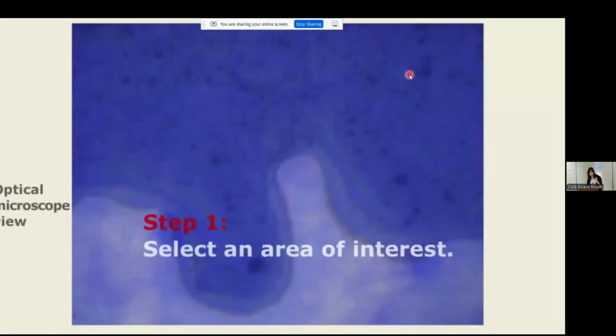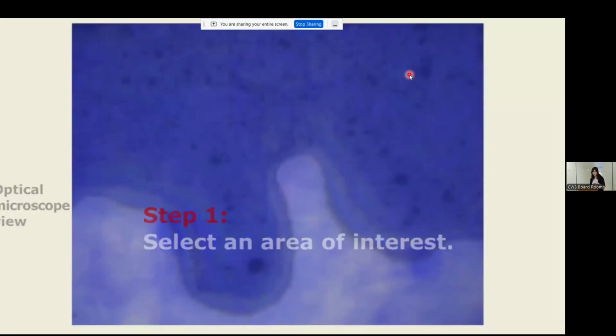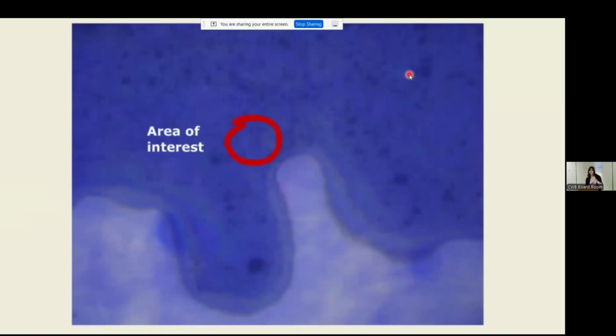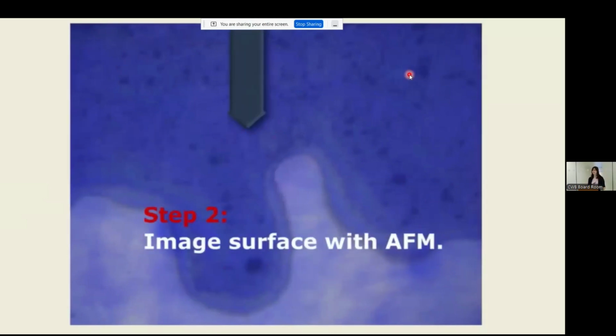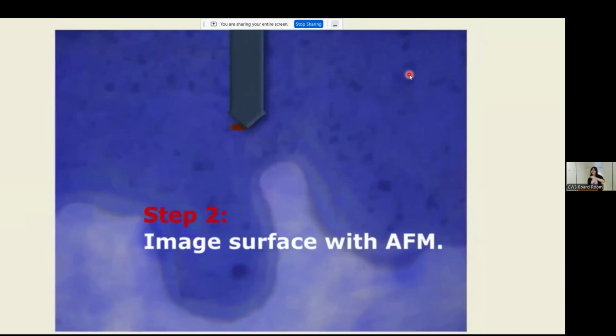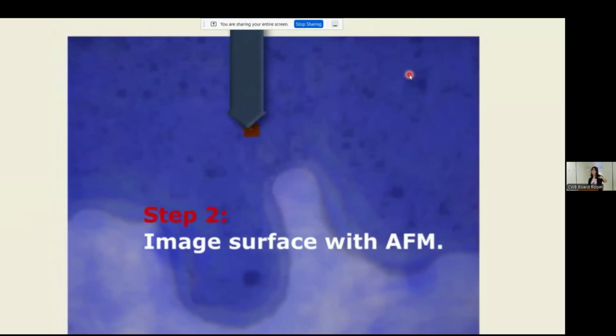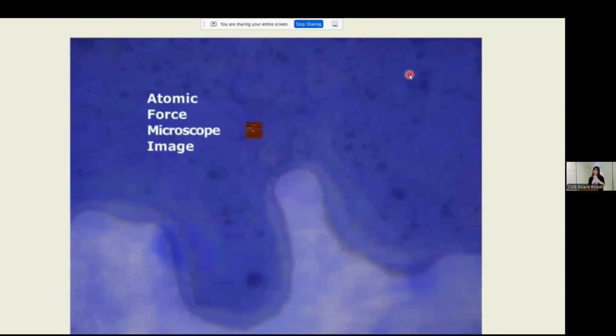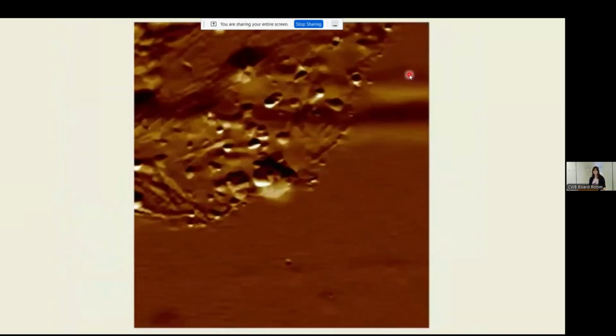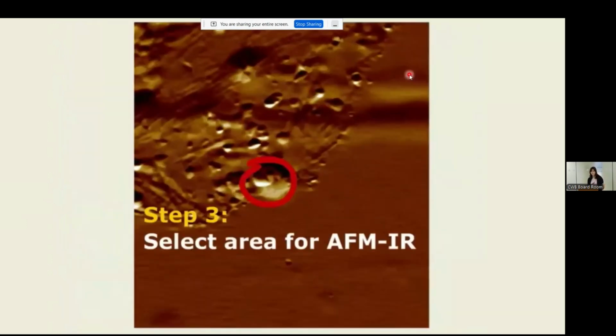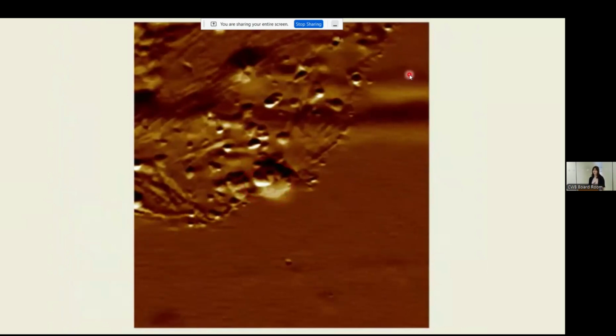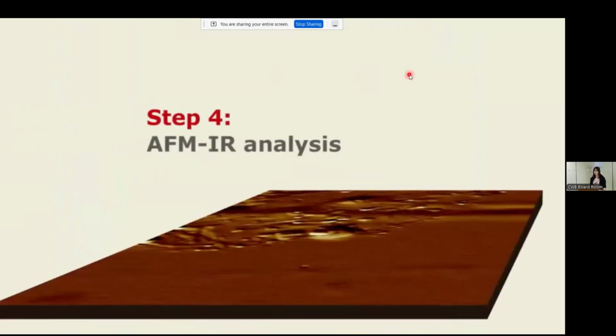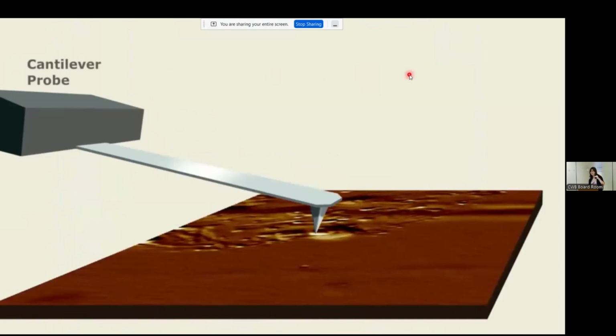And the video here now, the bitrate is maybe not the best of what that looks like, but effectively, we optically define an area of interest, and we use our AFM to scan over that material to find what we're actually looking for. So here's our image, and we identify, I want to look at this spot. We're going to put the probe on that particular location, and we're going to start to shine our infrared light on it. And that's going to cause this probe to start to wobble.